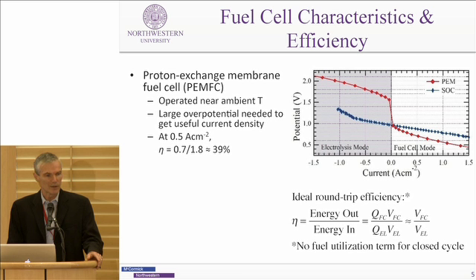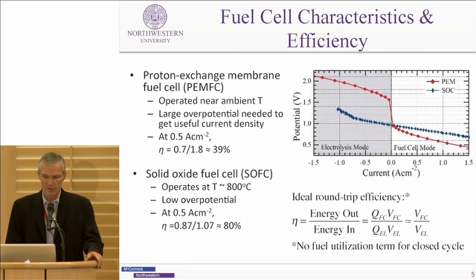If you assume you don't have a leaky system, these charges are the same, and it's basically just the ratio of these voltages. So if you go back to the PEM fuel cell case, 0.7 over 1.8 volt, that's only about 40% round-trip efficiency. So you're already behind the 8-ball with that technology.